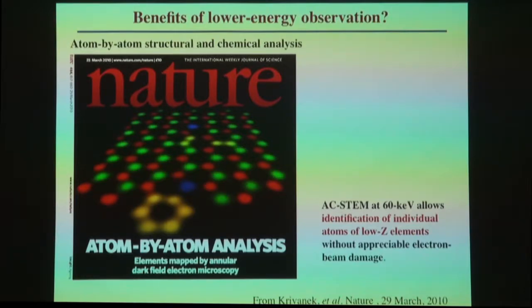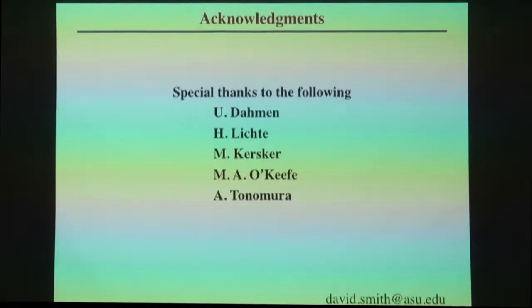But most of us, me in particular, I'm also interested in three-dimensional materials. These materials are not going to be able to withstand electron beam damage unless we go to lower voltage, but then you can't make the sample thin enough. So you have to compromise. Am I going to be at 80 kV or 200 kV? Am I going to damage the sample or am I not going to damage the sample?